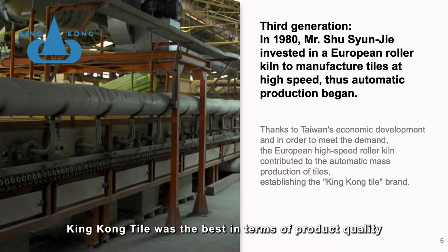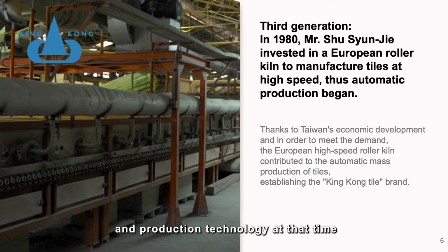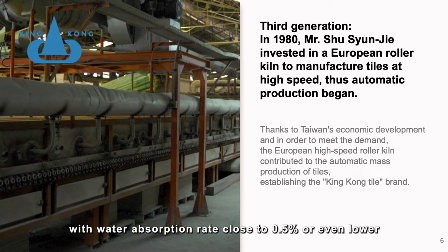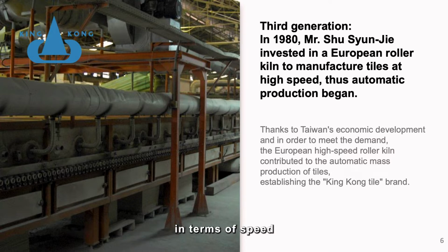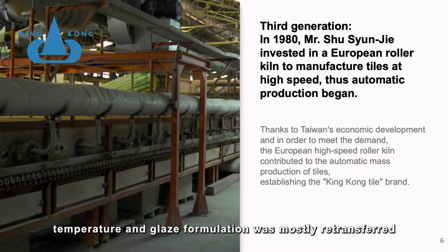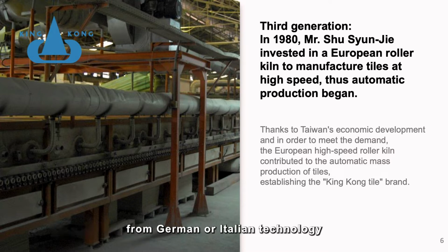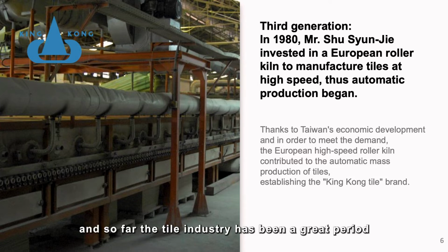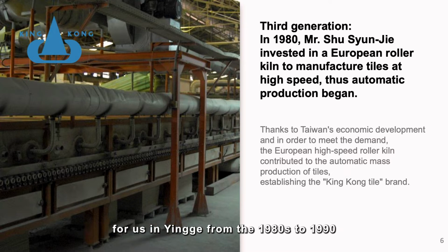King Kong Tile was the best in terms of product quality and production technology at that time, and we produced fully porcelain tiles and the so-called wet glazed quartz tiles with water absorption rate close to 0.5% or even lower. The firing process, in terms of speed, temperature and glaze formulation, was mostly transferred from German or Italian technology, and the tile industry was a great period for us in Yingge from the 1980s to 1990. Until now in 2021, the tile industry in Yingge is gradually declining due to the shrinking market.